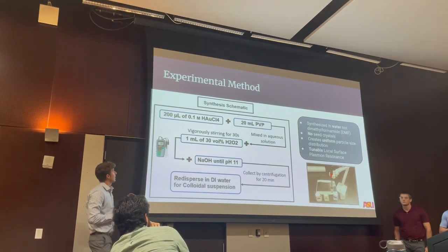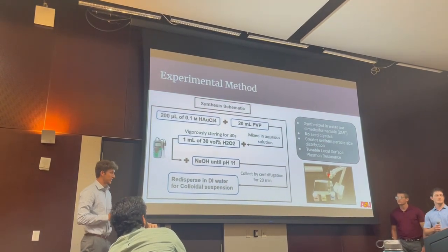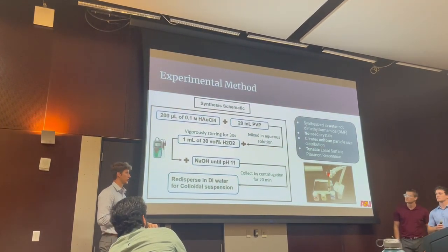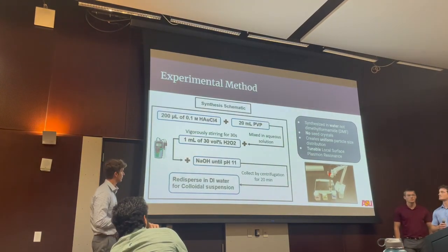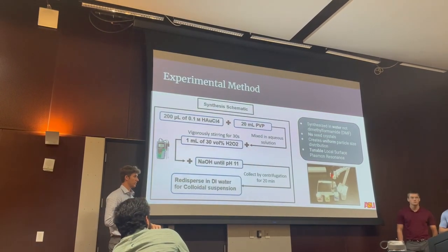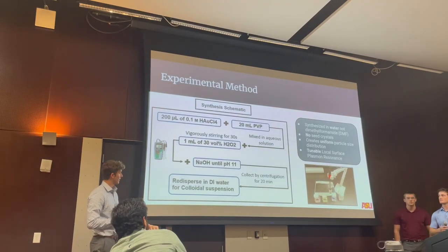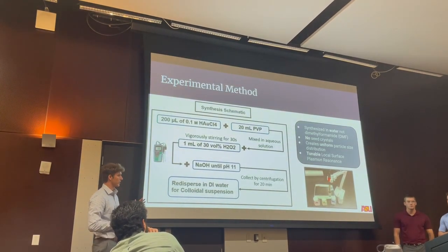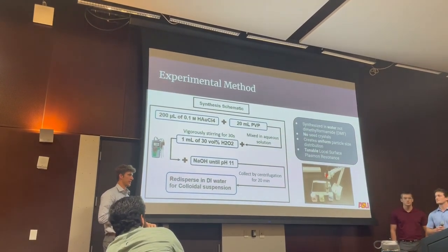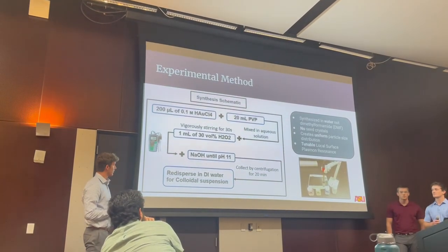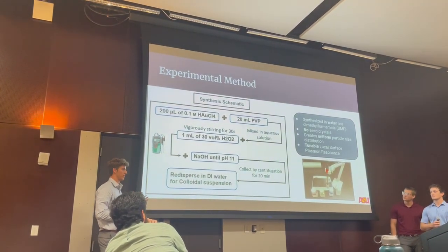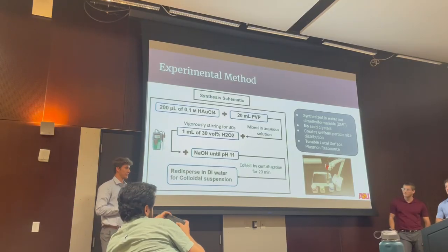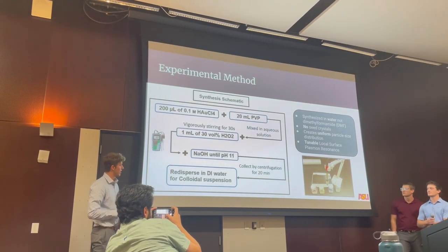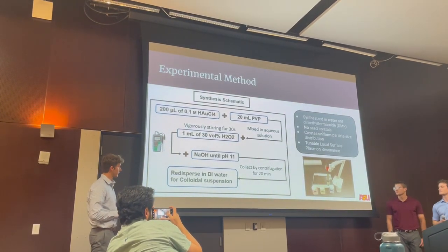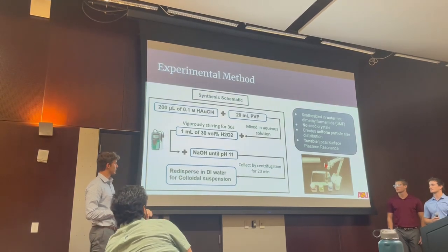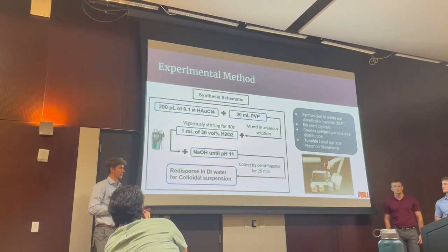So to go into detail on our experimental method, here's our synthesis schematic, which shows our 2 precursors. We've got a gold chloride salt along with our PVP solution, which is in PVP and DI water. And then you add in your H2O2, stir it for 30 seconds, which will start the particle growth. And then you go through a titration-like process with the NaOH until you reach a pH of 11 to stabilize the nanoparticles. So once that's done, you'll place them in the centrifuge, collect the nanoparticles, and redisperse them in DI water for a colloidal suspension.